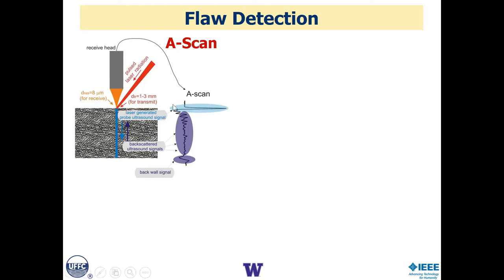So it's a laser ultrasound rubric. Again, you guys mostly know this pretty well. The idea is that for every one firing of our pump laser, with continuous recording of the received ultrasound signal, we get one line of information through the material, and that's an A scan like we have here. So that's a pulse echo ultrasound recording with non-contact detection through the material.